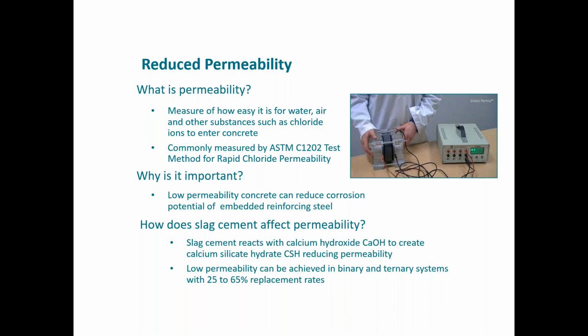What you're looking at is a single cell for a rapid chloride permeability unit. You have NaOH in one and sodium chloride in the other cell, those plastic cells the guy's got his thumb on, and strapped in between is a section of concrete. Typically it's a 4x8 cylinder. You cut, I think, a 2-inch section, strap it in, fill the solution up, and then you have a positive and negative lead to it, essentially forcing current through it and measuring the amount of charge that passed. So it's represented by coulombs.